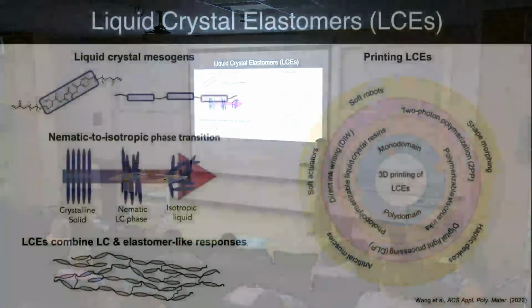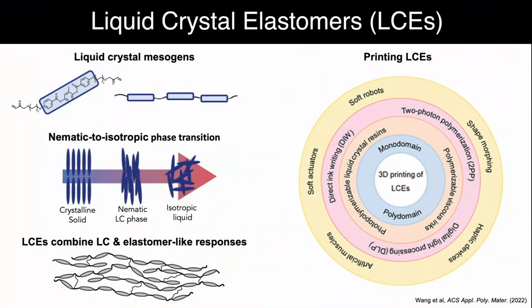Because we were relying on shear-induced alignment, we focused on mesogens in the backbone of oligomers, which we printed and, as I'll show in a minute, then cured and cross-linked to create the three-dimensional network. There are many different ways to do printing to pattern these liquid crystal elastomers. We've been focusing on direct ink writing, although we have a paper more recently out with the group at Sandia, where we use magnetic field-induced alignment in conjunction with digital light processing to also architect and control orientation.